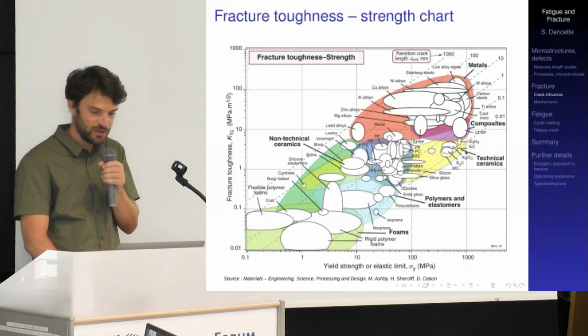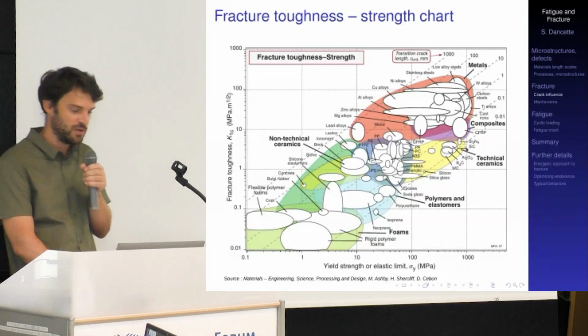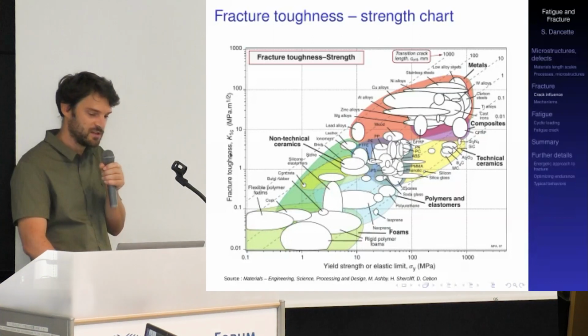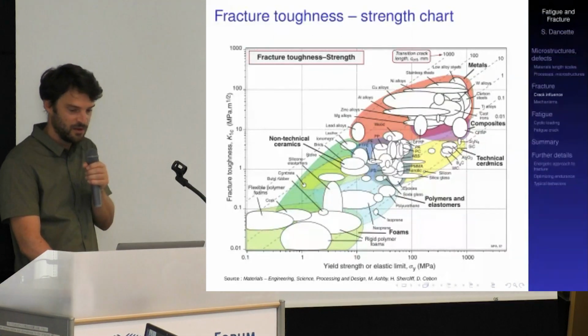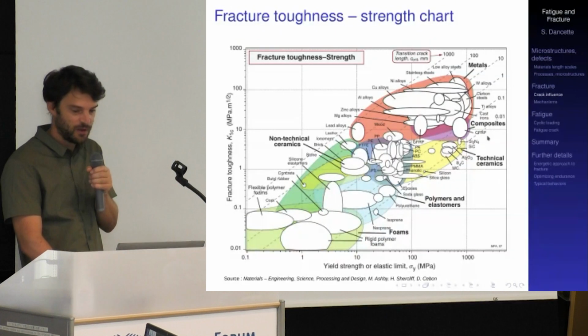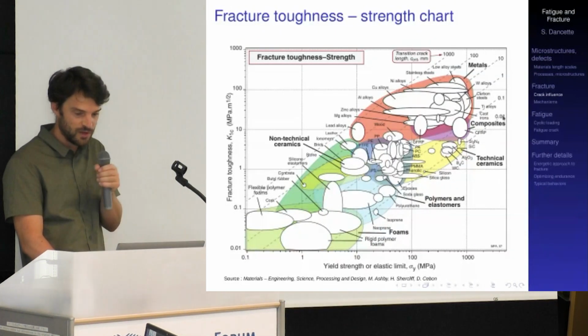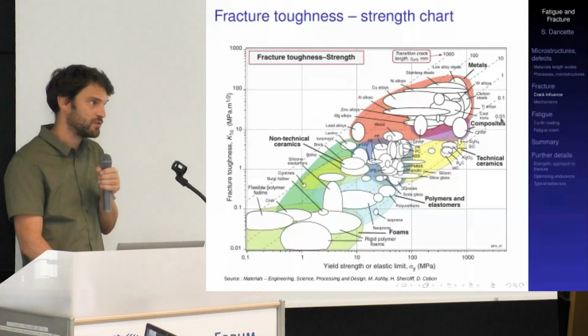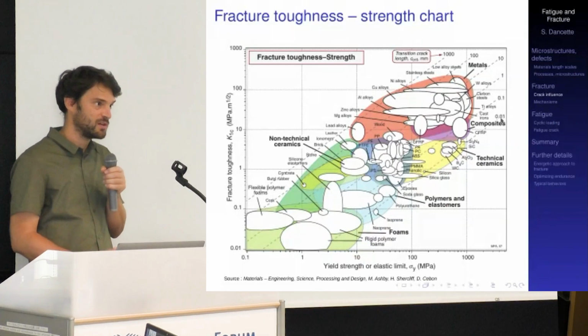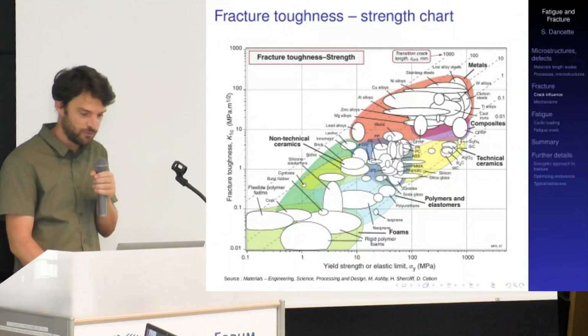But if you look at most ceramics, and if you look at the values of fracture toughness and yield strength in these materials, in ceramics, defects as small as a few, again, tens of microns will most likely be very, very detrimental for fracture.